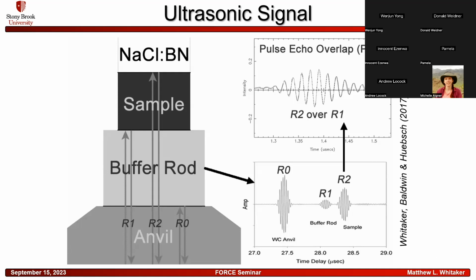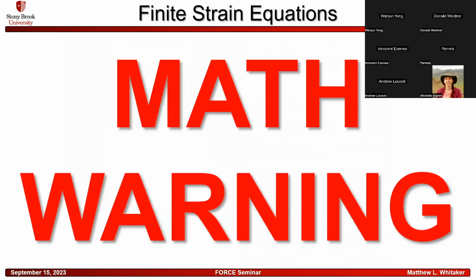And the way that we determine the travel time is we physically overlay the reflections for R1 and R2, which is the buffer rod sample surface and the backside of the sample. And that gives us the two-way travel time for the P and S waves in the sample.